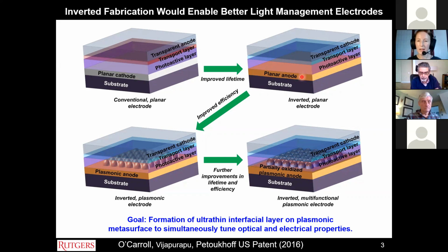If you switch it and make it an anode, so that the metal collects or injects holes, then you can create improved lifetime. This has been shown by a number of research groups. You can improve the stability of the device. And then in theory, if you add plasmonic structures to the metal, you can improve the efficiency as well.